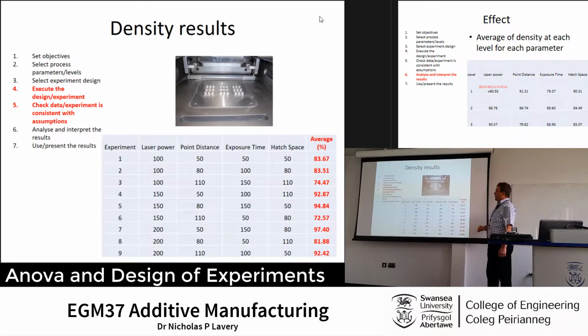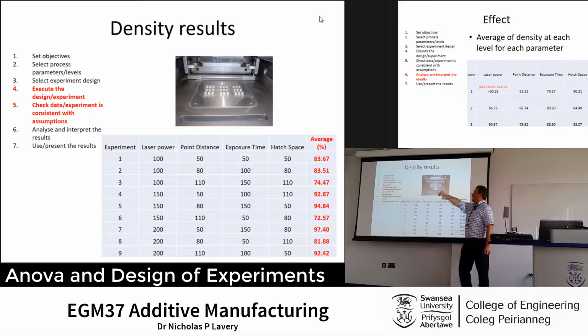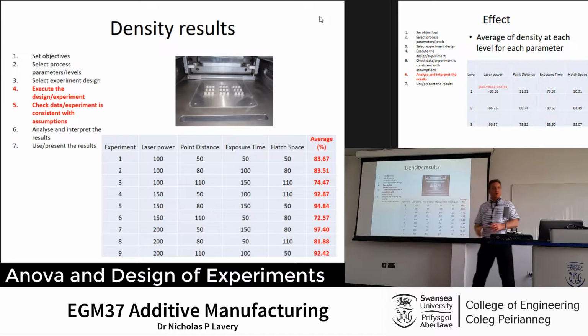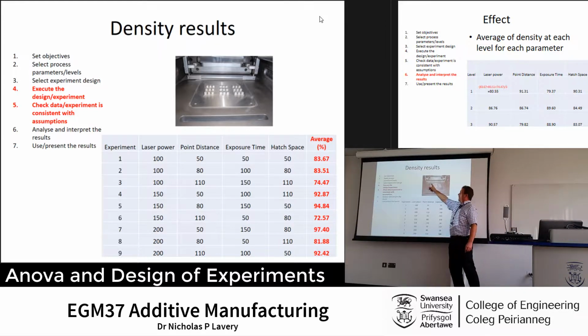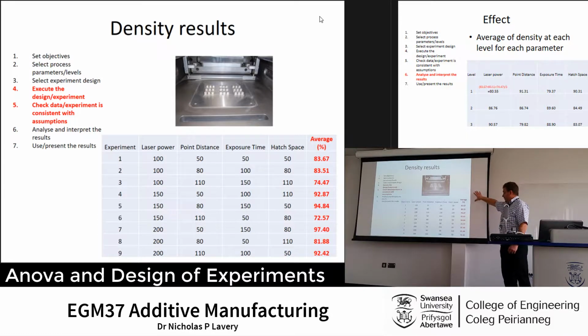Okay, so we build the parts. Here you can see it's an L9 array, but each component of the L9 matrix has got a repetition of 3, just to make sure we've got the repeatability of the test. Okay? And you can see there an average is given there, an average relative density for each of these from the 3 samples. You get then a range of different relative densities for different settings.